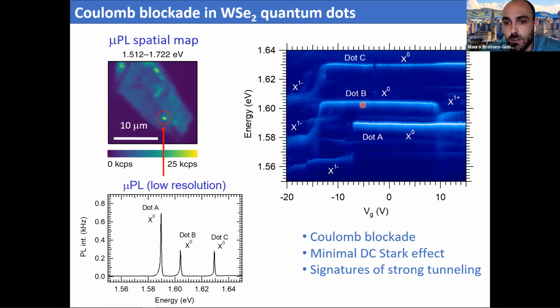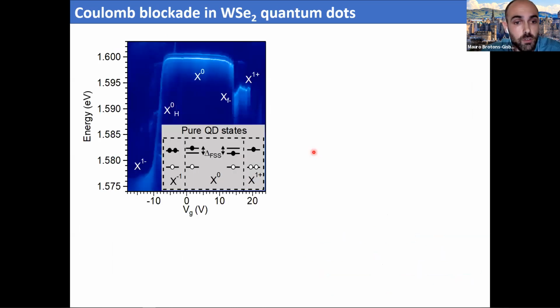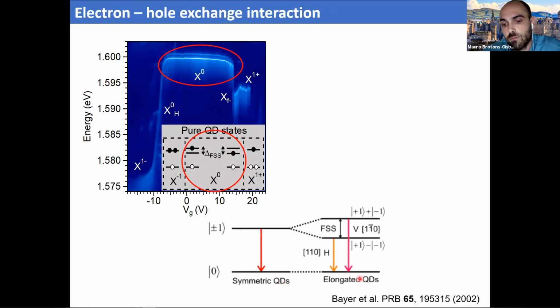So what we did was investigate dot B, because it has both the positive and negative trions, and you can see here the results. We used a higher spectral resolution, and the first thing we notice is that the neutral exciton is not a singlet emission line, but a doublet. This is typical of these quantum dots. It arises from a fine structure splitting, which originates from the fact that our quantum dot confinement potential is not symmetric, okay?